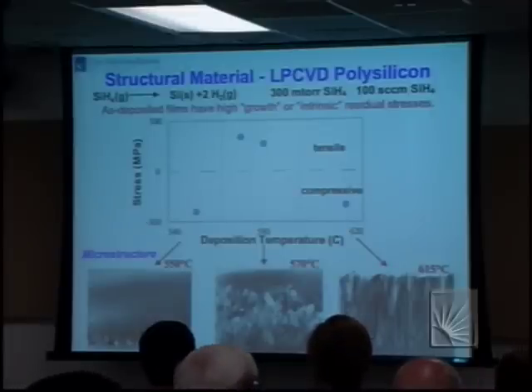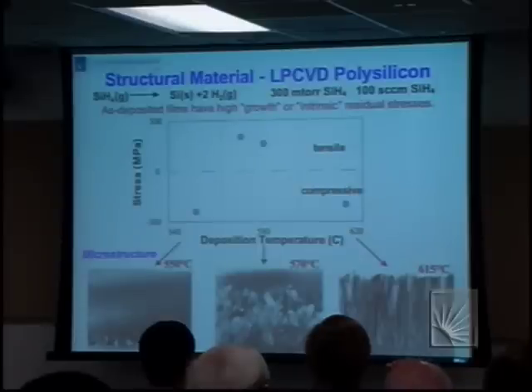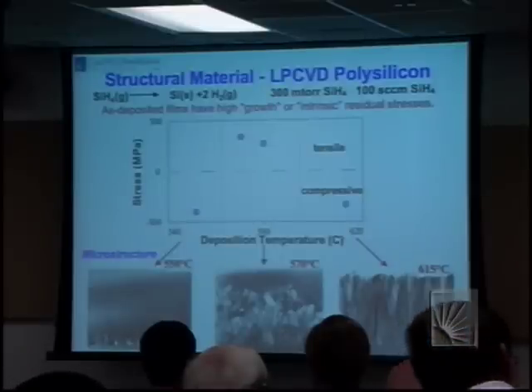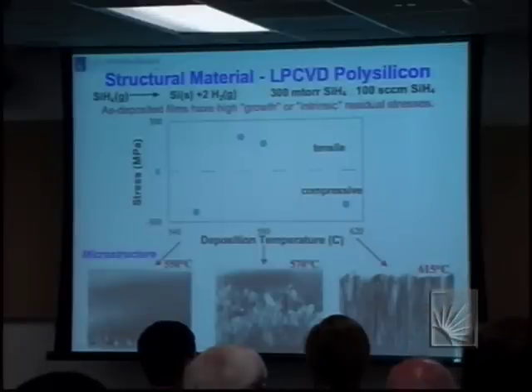At lower temperatures or at higher temperatures, the stress origin is different, and not as well understood. It's almost certainly a consequence of a non-equilibrium interstitial population. Whether it's interstitial silicons or interstitial hydrogens, we don't know, but outside the regime where you get these tensile stresses, there are non-equilibrium structures here and here, which cause compressive stresses. And compressive stresses actually are the rule rather than the exception in many different types of CVD deposits.